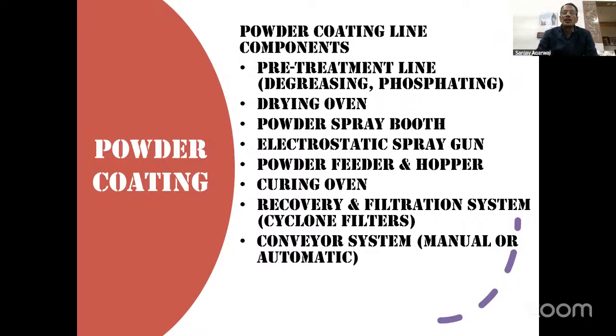Here we load the parts, clean the parts, then we spray the powder. The spray is done by electrostatic guns, and the leftover powder goes to the hopper. The powder coated parts go to the curing oven, and stay there for 30 to 40 minutes at a temperature of 220 degrees. There is also a cyclone where we recover the leftover powder in the booth, and it has to be filtered.